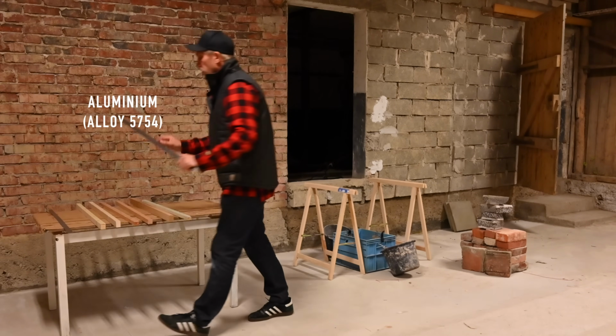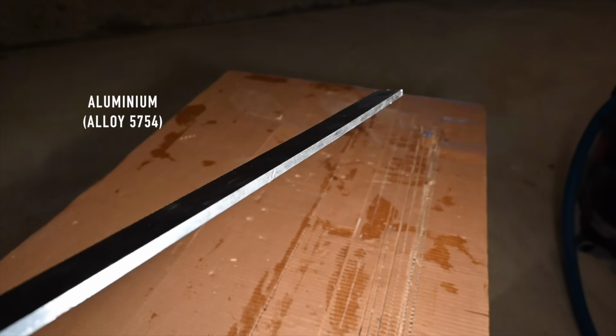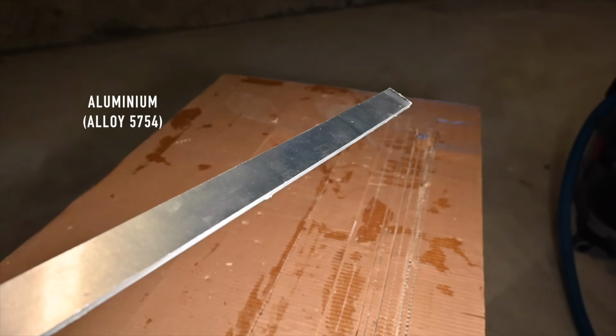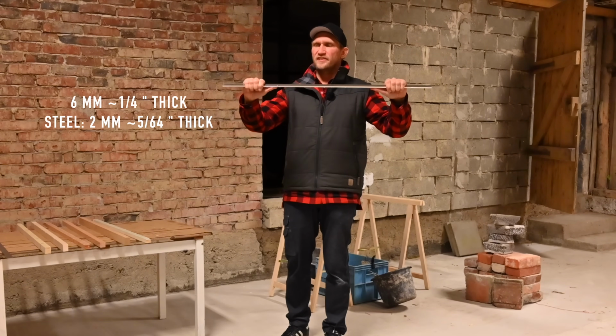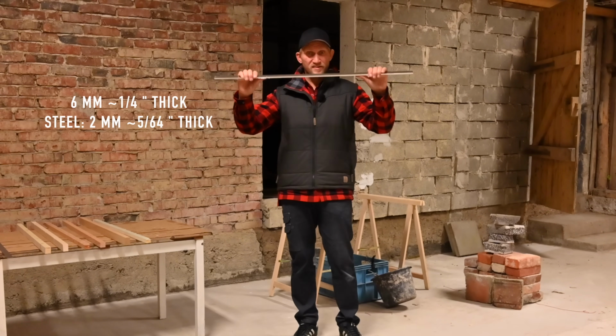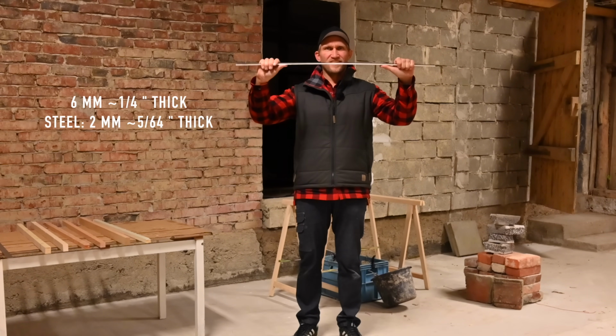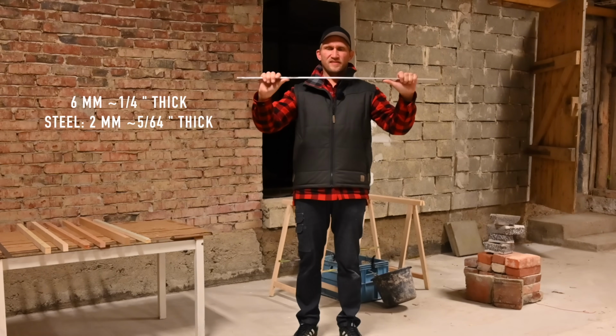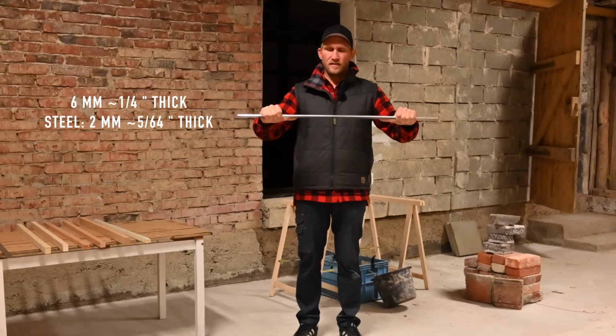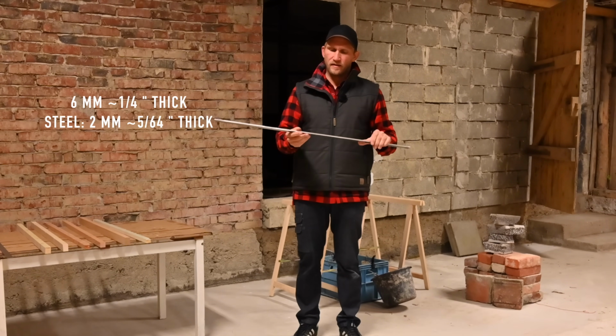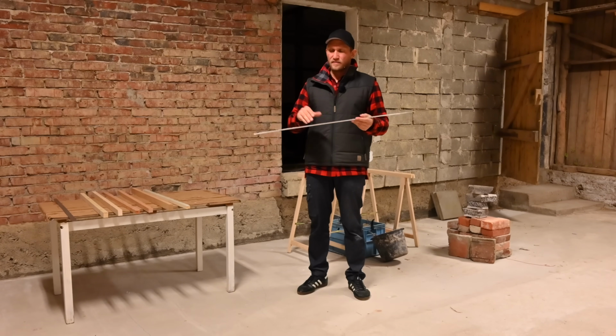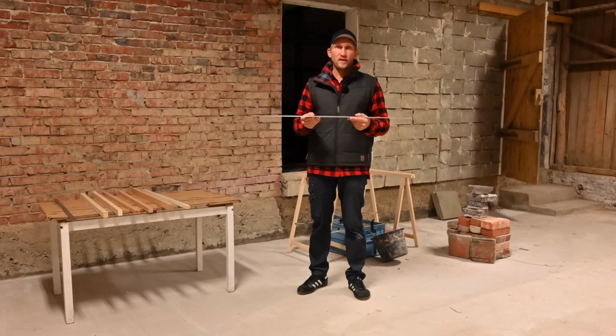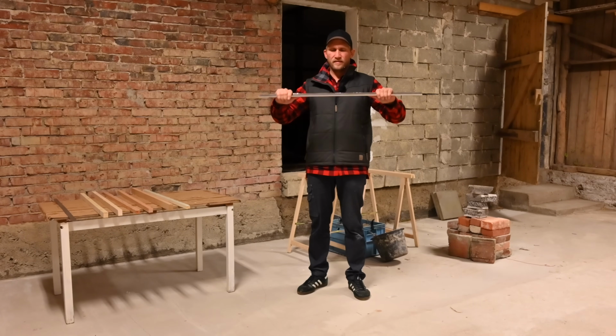Next up we have aluminium, and this is a cool material in my book. This is 6 millimeter. The steel sample was 2, but it's the same weight, but you can already see that the force that I need to put on this to bend it is a lot more than I need to do with the steel. They say that aluminium is roughly 3 times as strong as steel by weight. And you can really tell that when you're just doing like this.